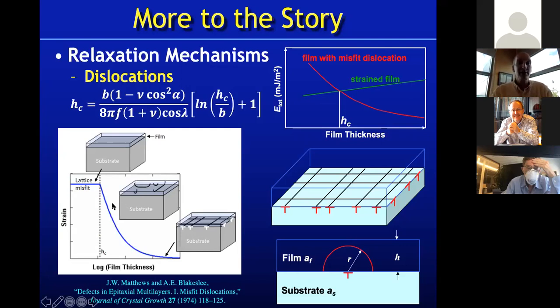And then as the film gets thicker and thicker, you start to see that strain relax. It relaxes in a very inhomogeneous way. There are these inhomogeneous strain fields. Okay, so for doing strain engineering, I really recommend staying in the regime where one has a commensurately strained film, where there are not a bunch of dislocations that have inhomogeneous strains, but rather one can see the intrinsic properties of the ground state that you stabilized in this homogeneously strained commensurate film.